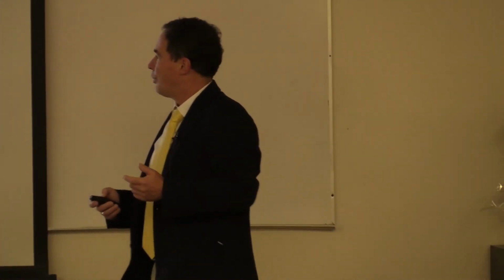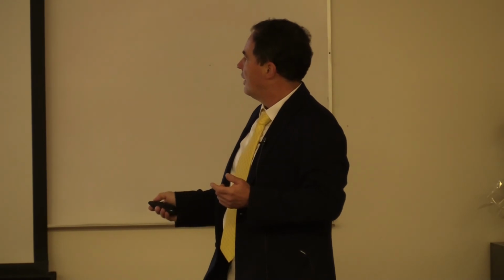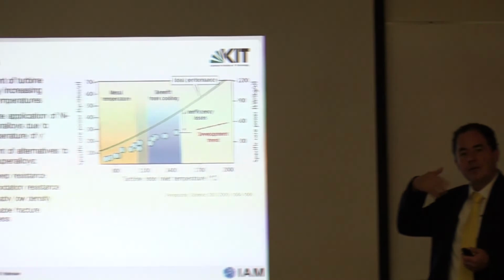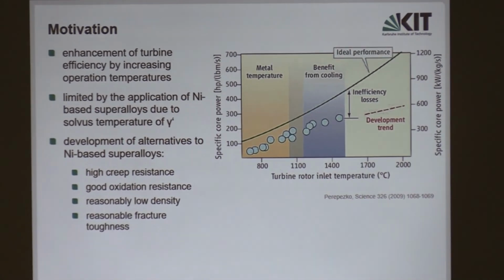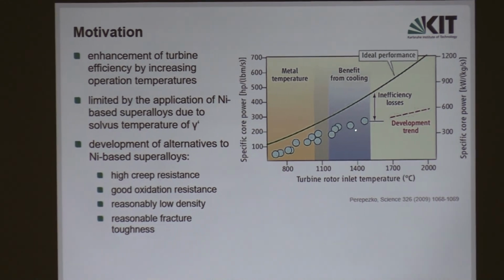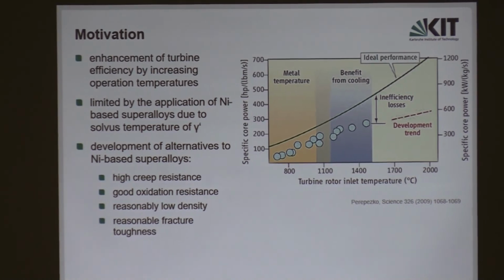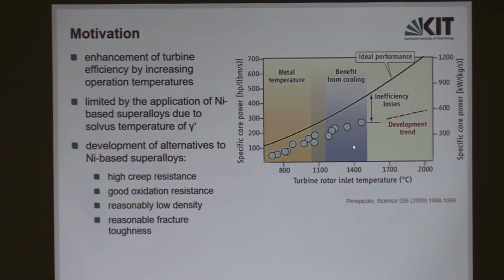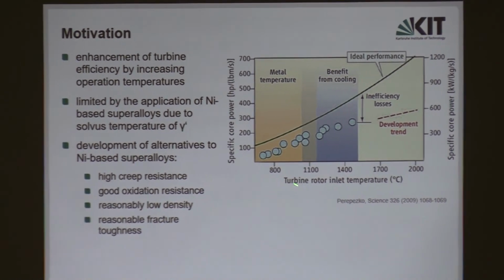That can be actually quite precisely answered. In this first slide, where I showed you the temperature increase with the efficiency increase of the engine, I can try to go back. Here, every 100 degrees Celsius gives you an improved fuel efficiency of 5 to 10%. As you see here, the temperatures are much higher than the temperatures a nickel-based superalloy can withstand. So there must be alloys which can withstand 1400 degrees Celsius turbine rotor inlet temperature.